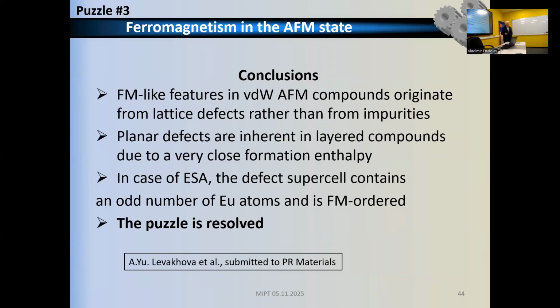You grow the sample at 600 Kelvin or maybe 1000 Kelvin, so the defect can naturally emerge at this elevated temperature. Okay, the defect supercell contains an odd number of europium atoms, and therefore gives birth to the ferromagnetism.